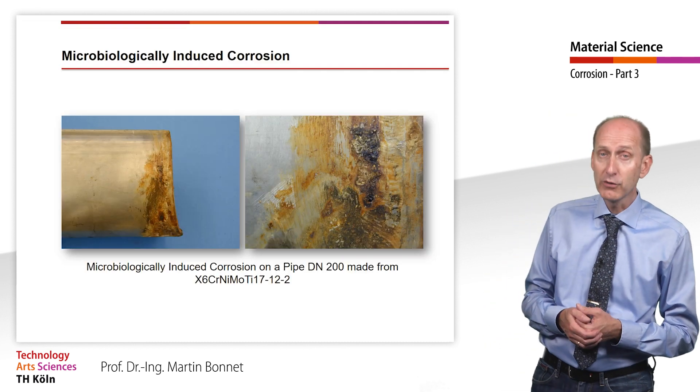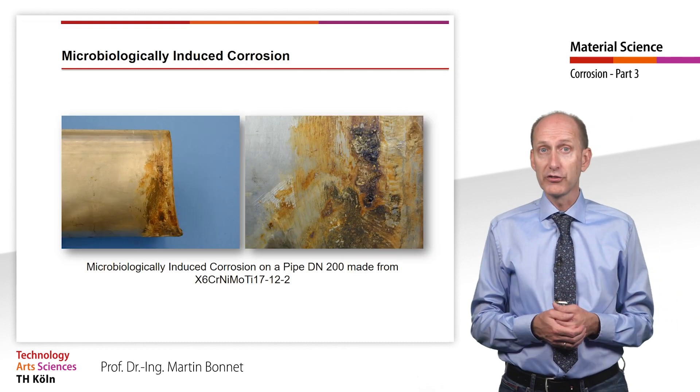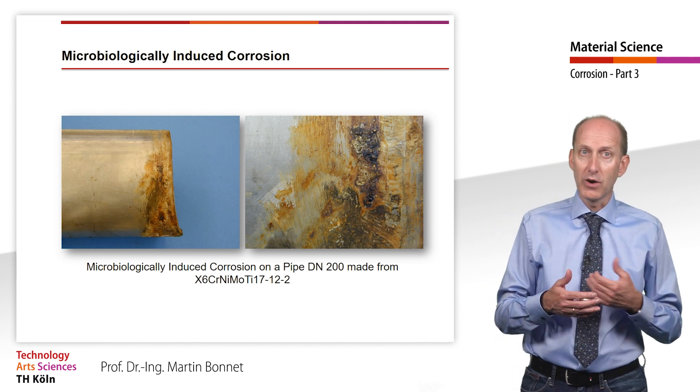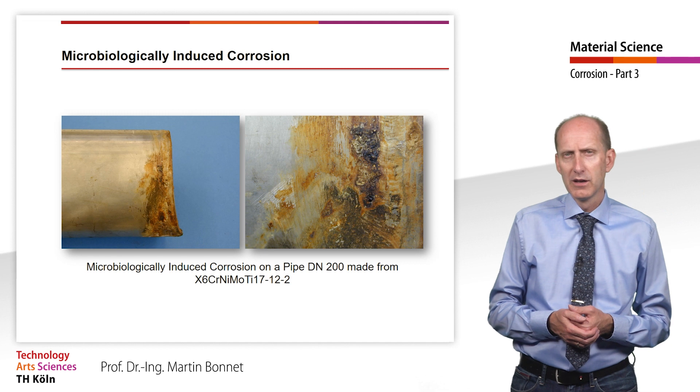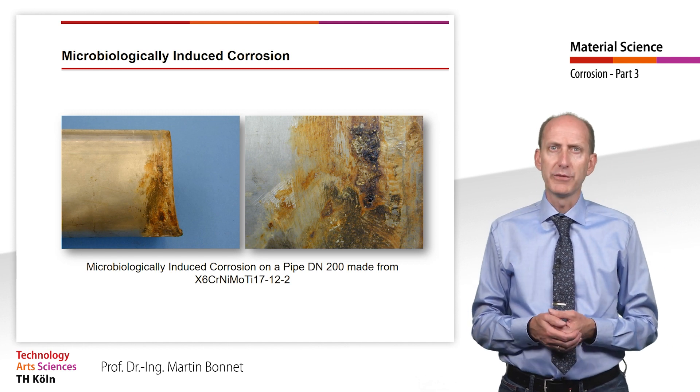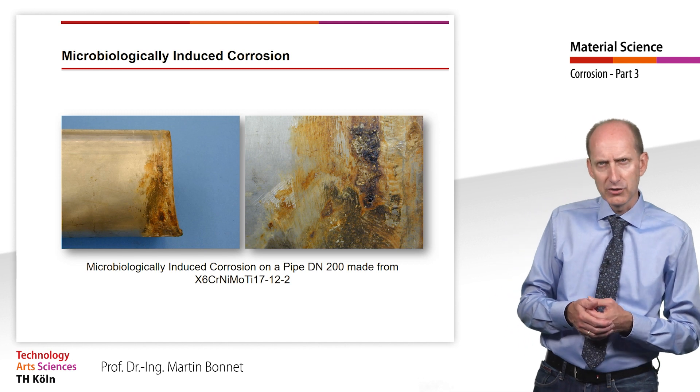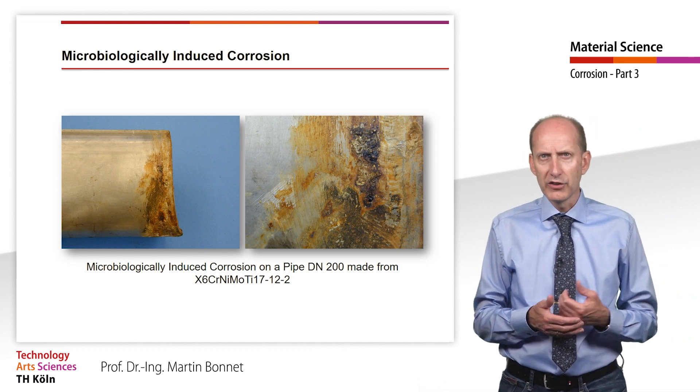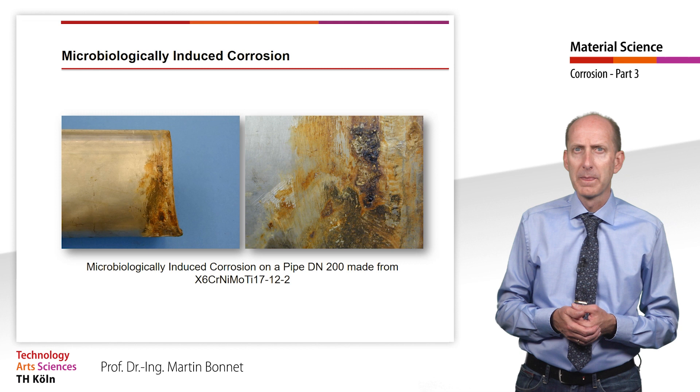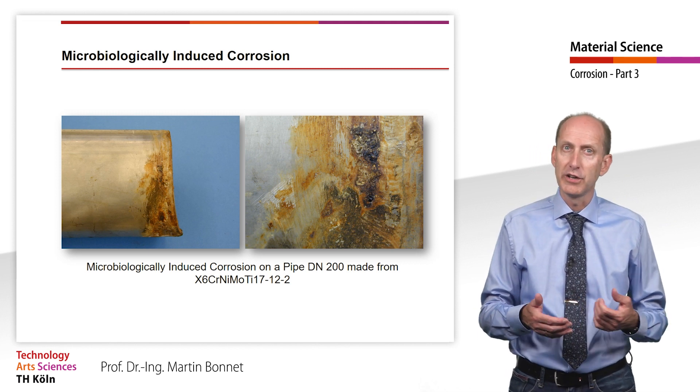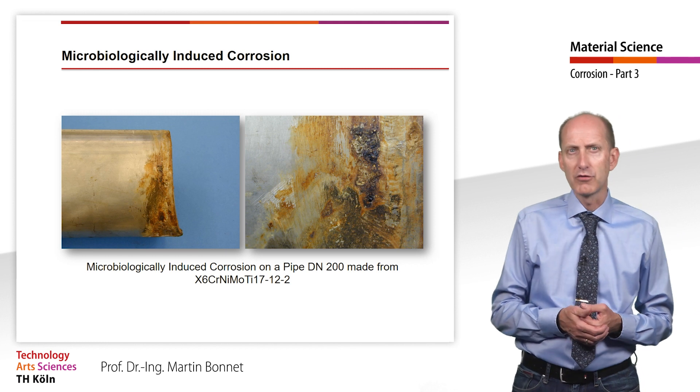Surprisingly, microorganisms can also cause considerable damage to metallic materials, even to high alloy stainless steel. Once a biofilm has formed in which the microorganisms feel very comfortable in a gel-like mass consisting of so-called exopolymers, manganese oxidizing bacteria, for example, can join in and set rapid corrosion in motion.